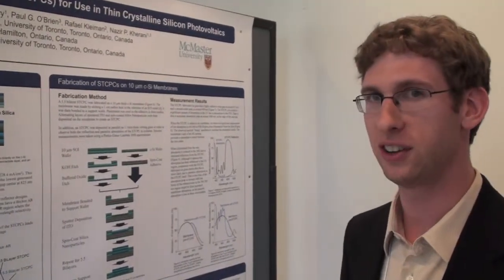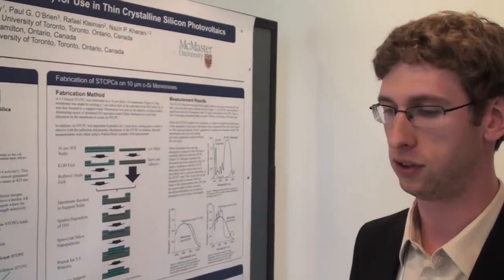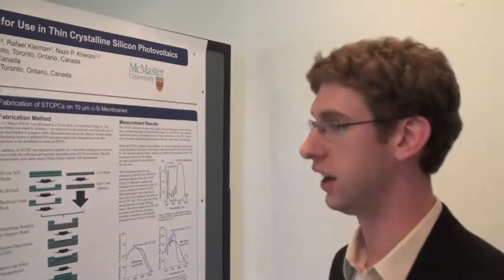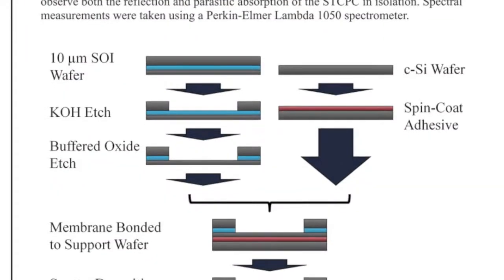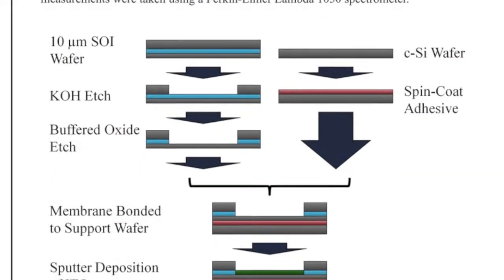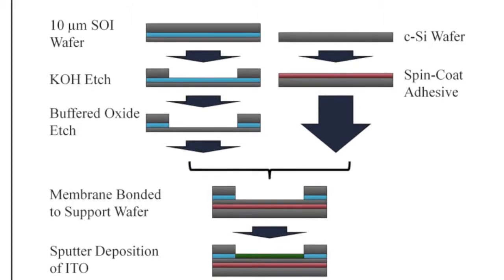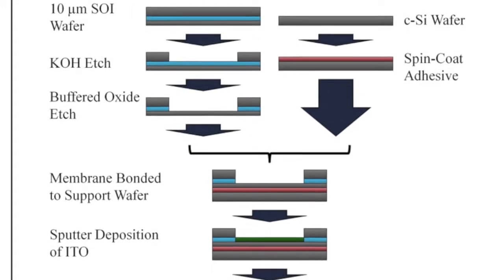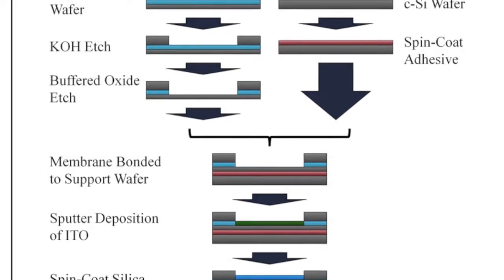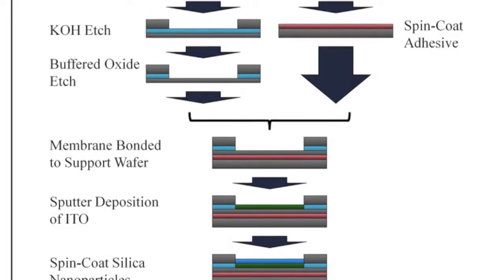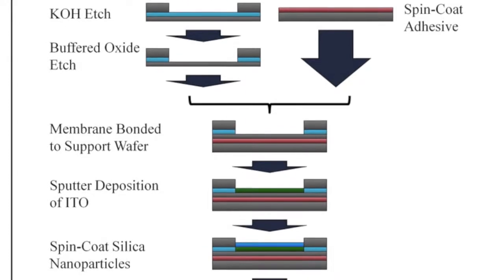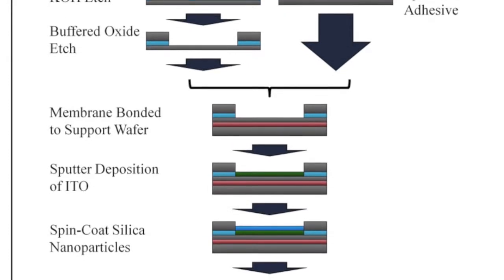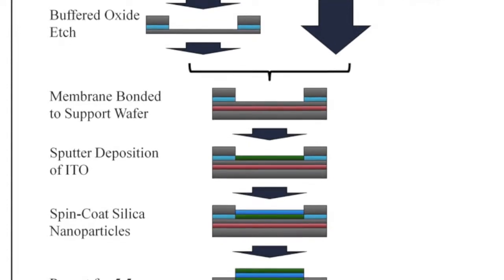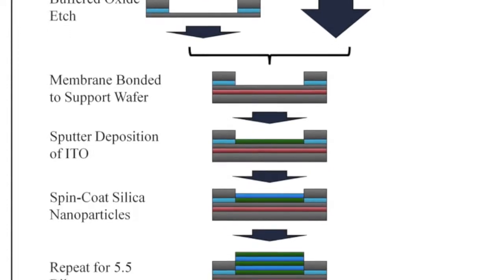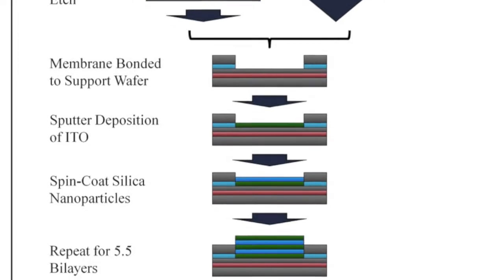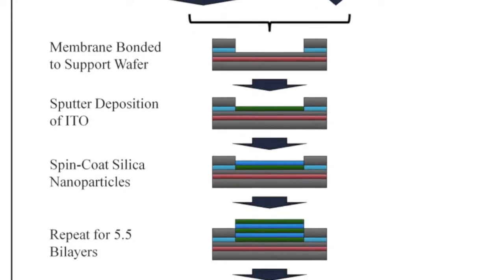Because it's very difficult to handle silicon membranes, we start with a silicon on insulator wafer, which has a 10 micrometer layer, followed by silica, followed by a much thicker layer, and then etch away down to a smaller membrane. By doing this, we give ourselves room to actually handle the wafer with tweezers, which is pretty important when you want to go through the process. But this is something you just do in the lab. In an actual fabrication industry format, you would just use the whole thing being a 10 micron planar crystalline silicon.